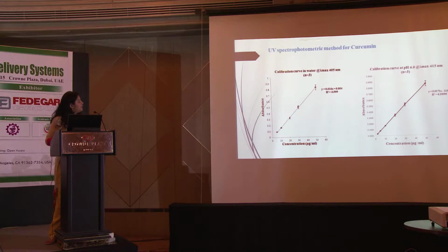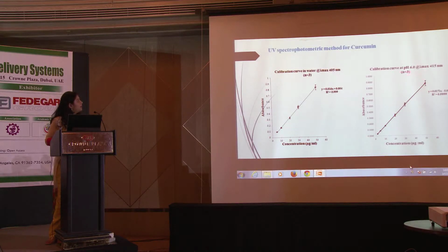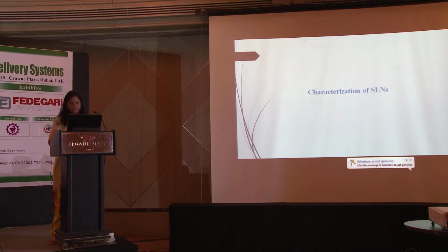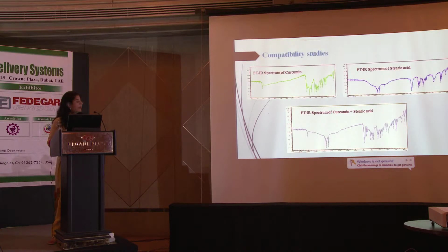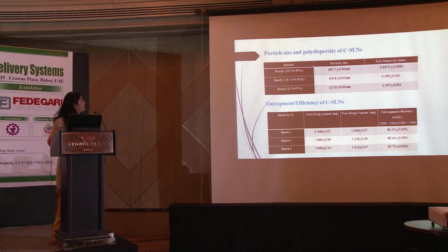This was the UV spectrophotometric method. We developed two methods, one in water and the other at pH 6, which is around skin pH, and we got pretty good curves in both of them. We did compatibility studies by FTIR for curcumin and stearic acid, and we found that the excipient and the drug were pretty compatible.